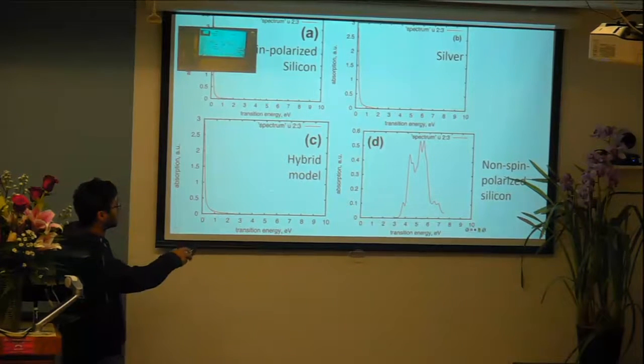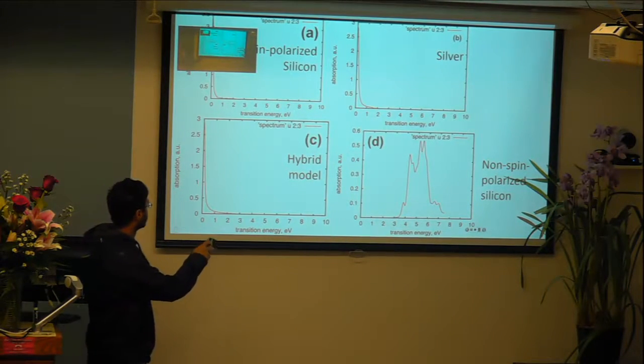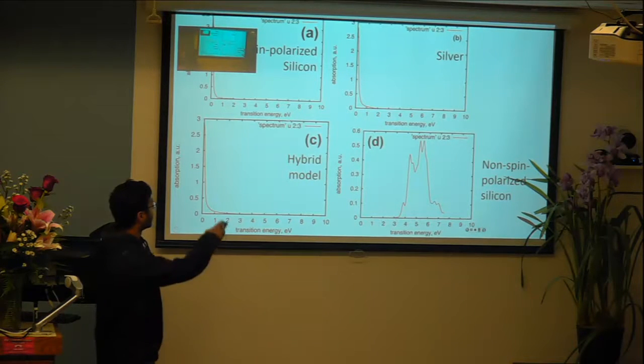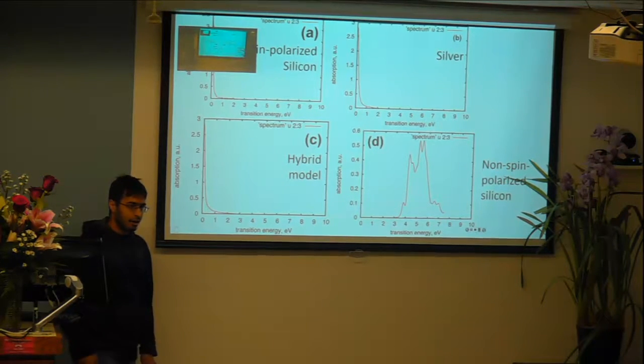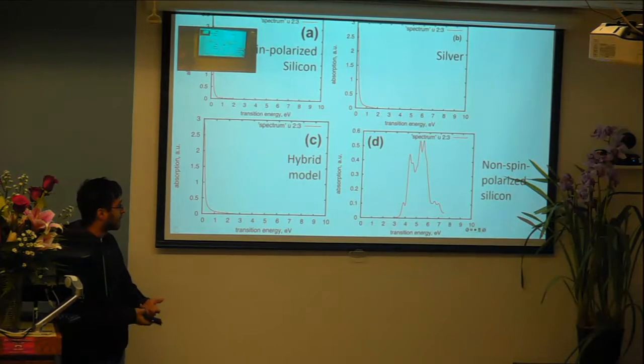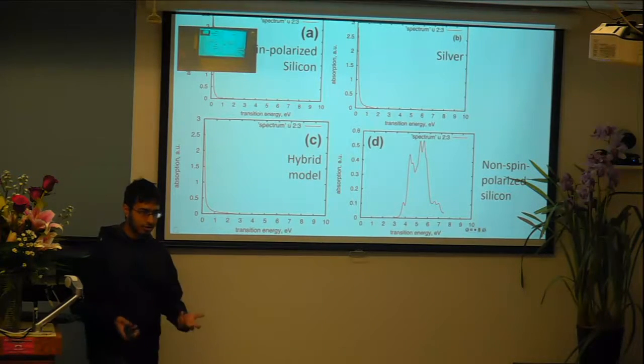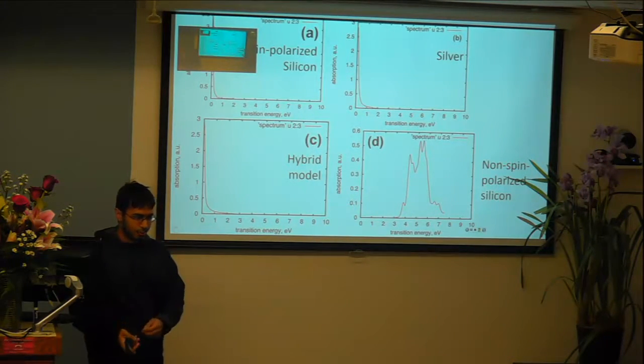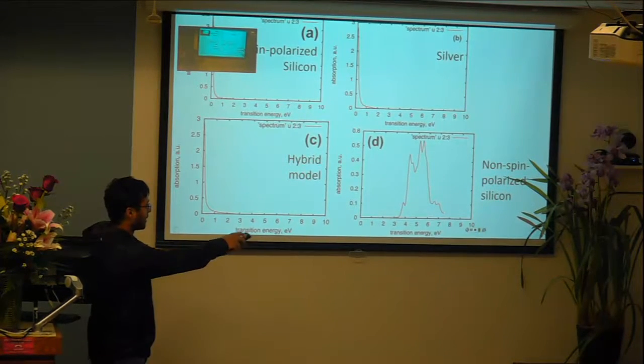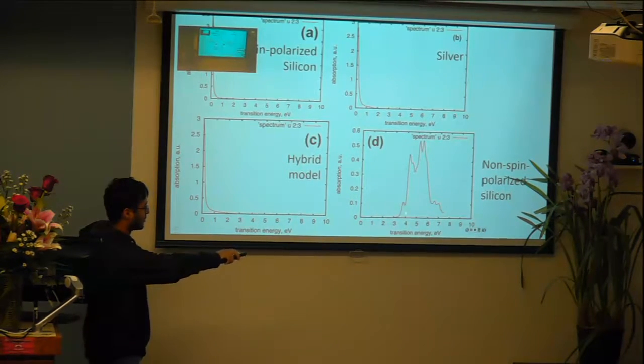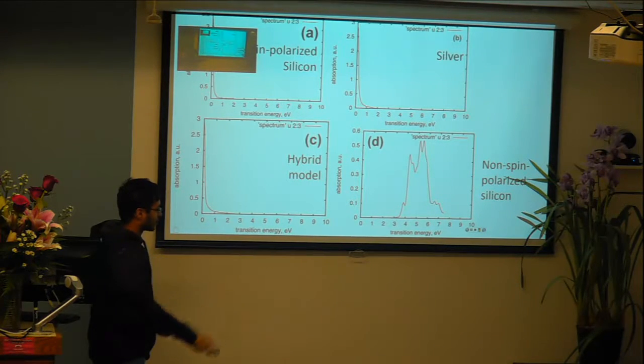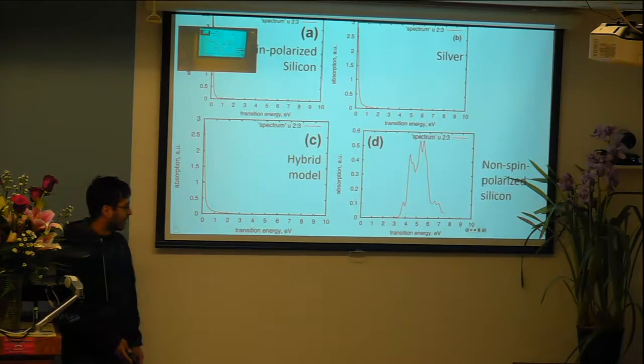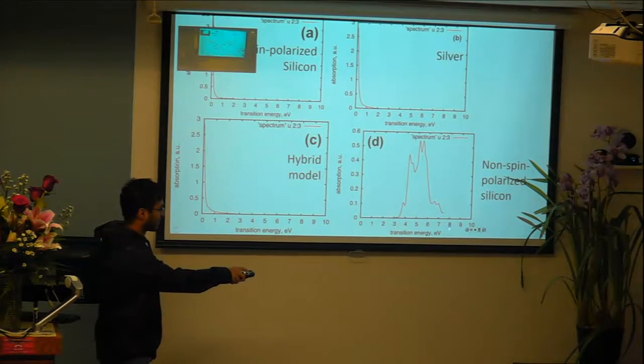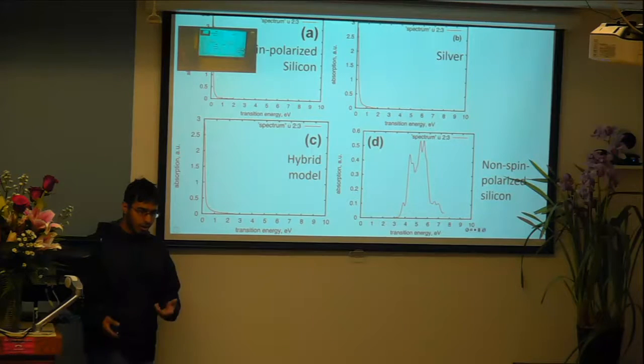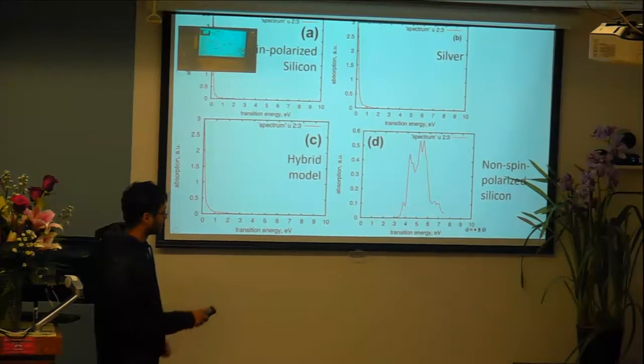So on this slide, we have a couple of different absorption spectra. And for the first 3 plots, there's a very large peak near 0 energy, signifying that incident light would have to have a very large wavelength in order for an electron to move to a higher energy state. And then on this lower right-hand plot, you can see that there are peaks at a higher transition energy, signifying that ultraviolet light can actually excite electrons from a lower state to a higher state when these electrons absorb photons.